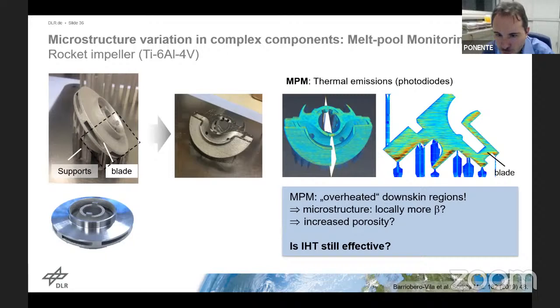And what you will immediately recognize in this data is the increased heat in the downskin areas. These are known to overheat. And you also recognize that there are other regions in the part that show a little bit increased intensity, and regions that have a lot less thermal radiation in the MPM during the melting time. So the question here is, what's the microstructure in this manufactured part finally looking like? And is the same microstructure with the 6 to 7 volume percent of beta phase still achieved? So is the intrinsic heat treatment from the parameter that we got from the cube study still the same, leading to the same result here?